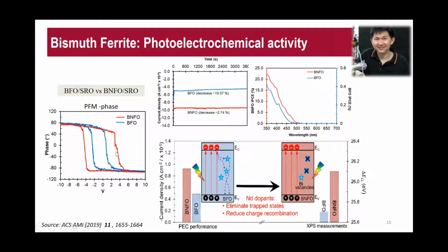BNFO, that is Nd-doped BFO, has a very wide area in the hysteresis loop compared to BFO. And how would this contribute to the PEC activity? Knowing that having this wide area, we assume that it definitely reduces the potential leakage. And we checked the current density in terms of the stability, and we found that BNFO, the BFO doped with Nd, indeed has a much more stable response compared to BFO. And in terms of the IPCE conversion, BNFO behaved much better.